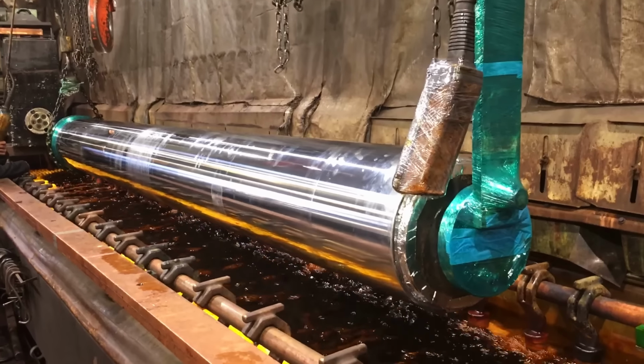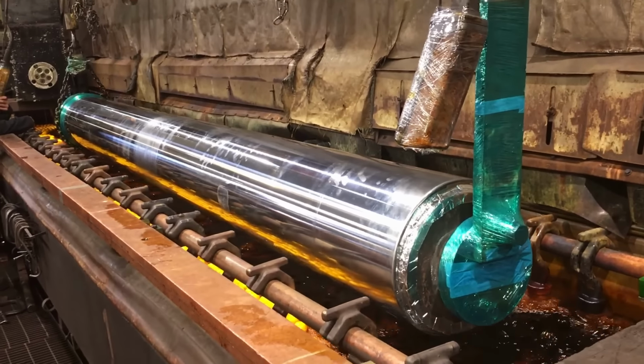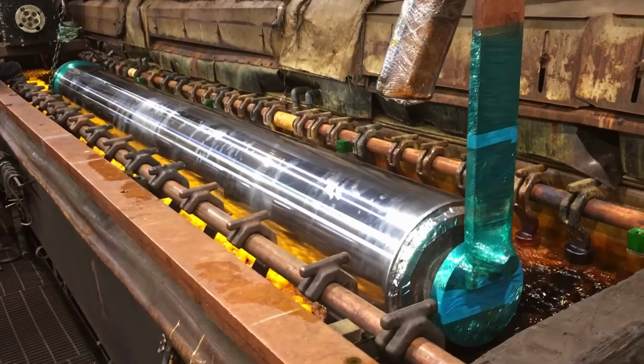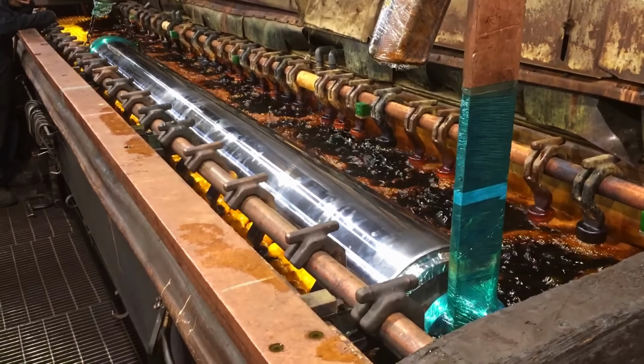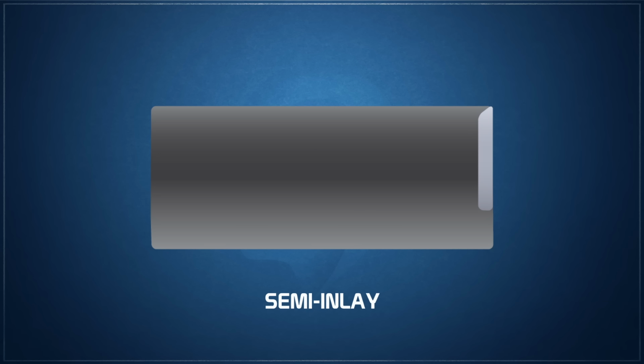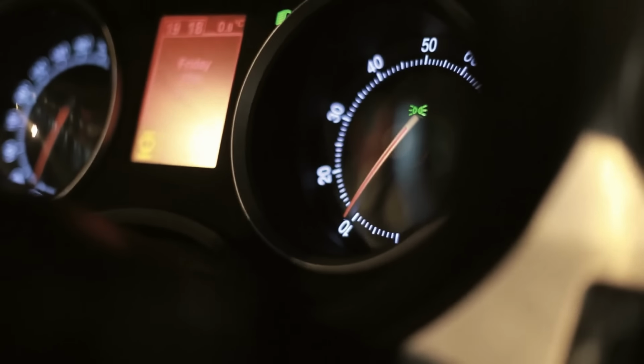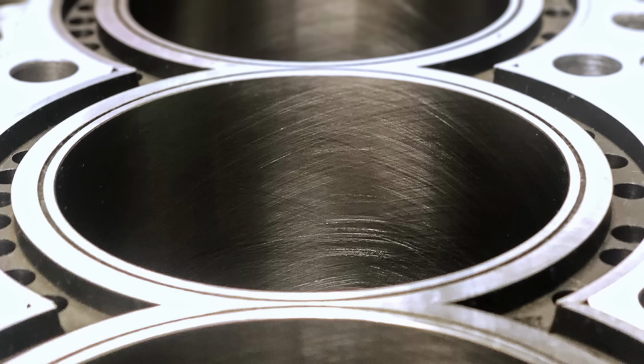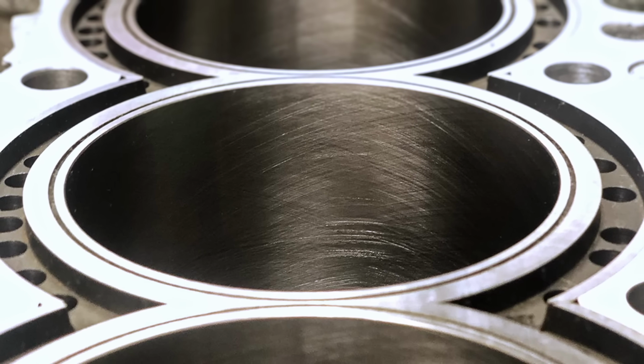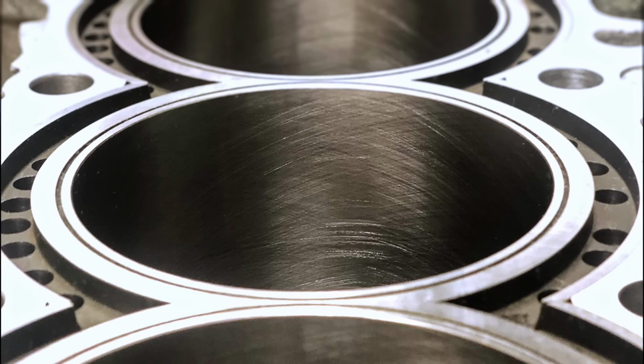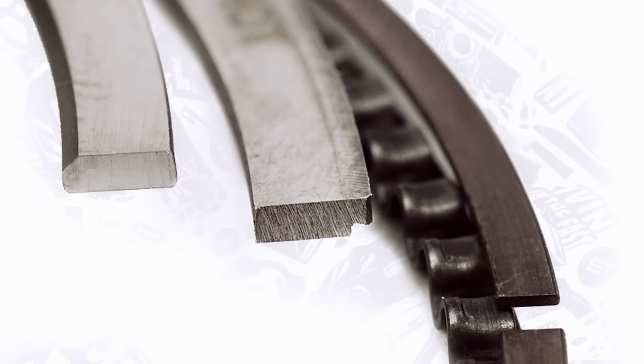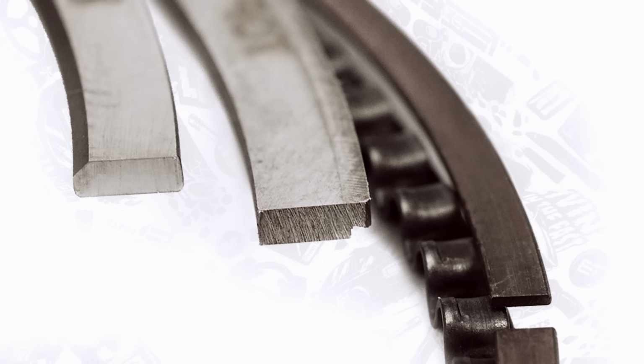The advent of hard chrome plating in the late 1930s allowed cast rings to achieve almost 3 times greater face hardness. Applied using galvanic processes as either a full face, an inlay, or a semi-inlay coating, it provides a high durability, hard, non-sensitive surface that prolongs engine life. It does require a longer engine break-in period to establish a working surface, often requiring a more aggressive bore surface finish to aid in this break-in. It also lacks the dry lubricating properties of a cast iron surface for emergency use.